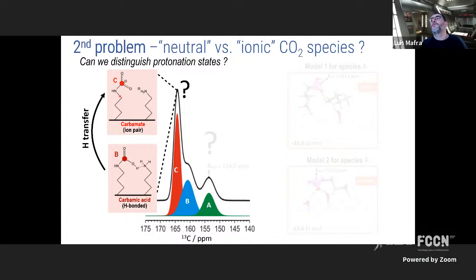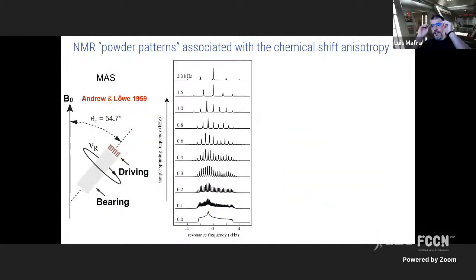We tried to use a different technique. In NMR, you need to put the powder in the sample, as I said, and you need to spin the rotor. This is something I didn't say. When you spin the sample, if you don't spin the sample, maybe it's better to start like that. At 0 kilohertz, you have a powder average, so you have a powder pattern. Okay, so in NMR, molecules are not tumbling like in the liquid, so you have zillions of different orientations.